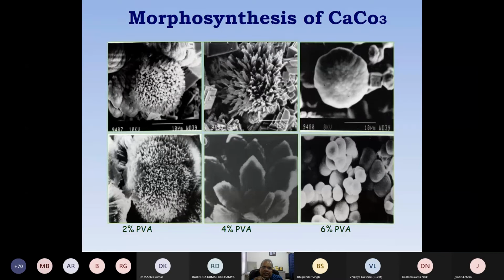So we took 2%, 4%, and 6% PVA solutions, put in the calcium ion, and gave it around a week for interactions at ambient temperature. We did not disturb it. Then we passed carbon dioxide gas through those three reactors. Then we saw a white precipitate. We took the precipitate, the particles, out, scooped it out, left it to dry under ambient conditions, and then we saw it under the scanning microscope.